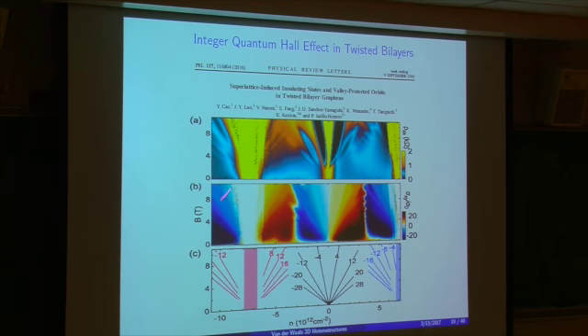And so what is interesting is to look at these satellite insulating states. So we have the usual bottom of the Dirac cone for the graphene, that makes it so that there is very little conductance in the middle. But here, these states left and right come from the opening of gaps due to this superlattice.